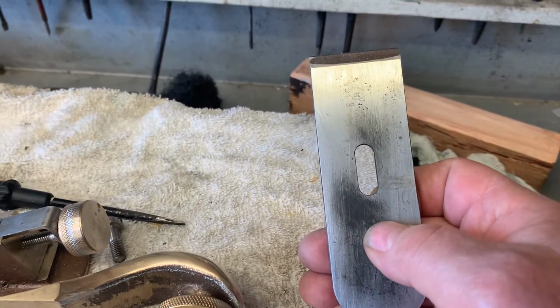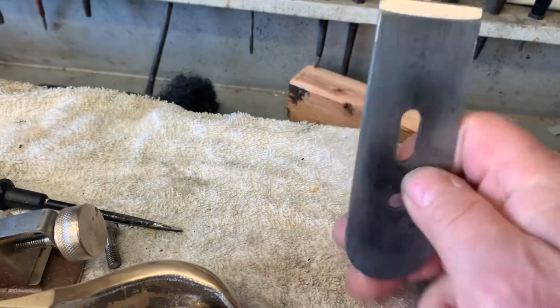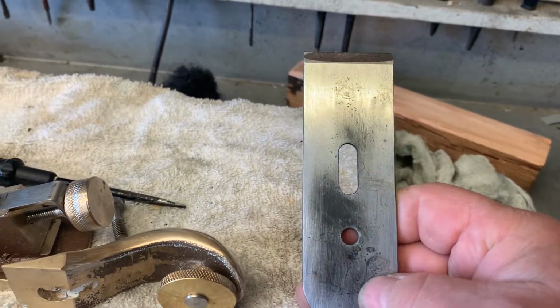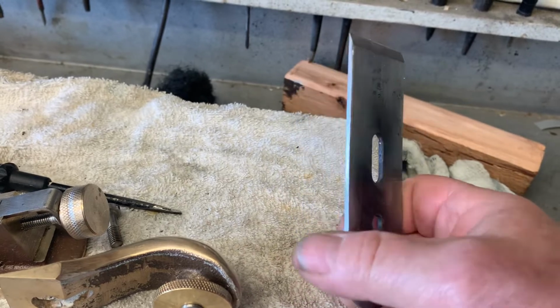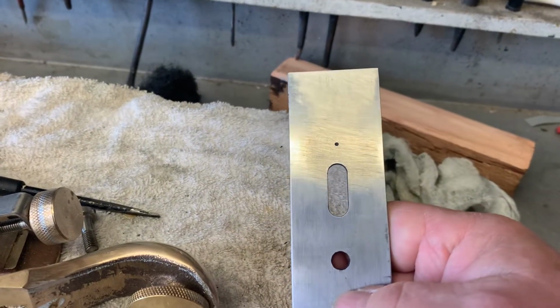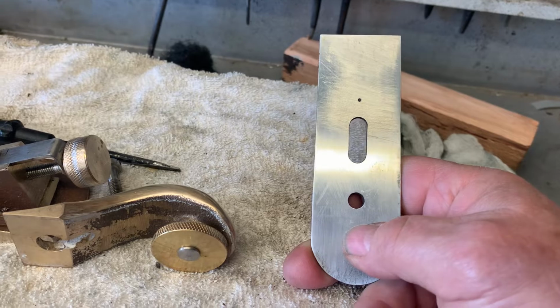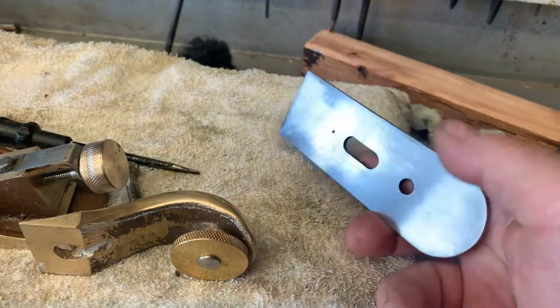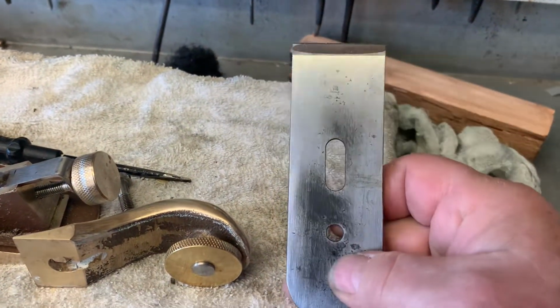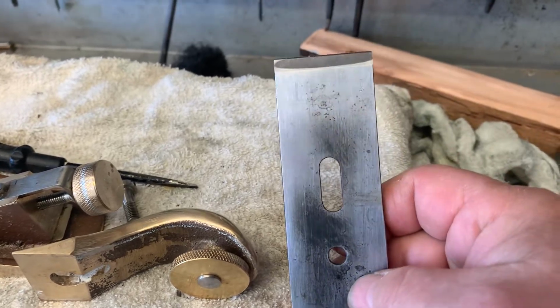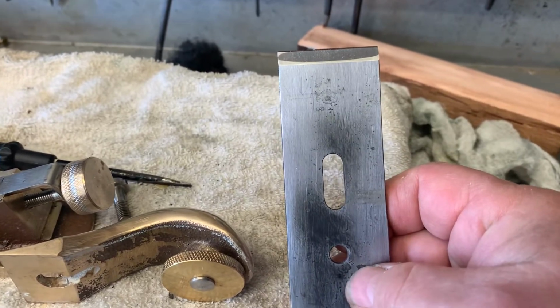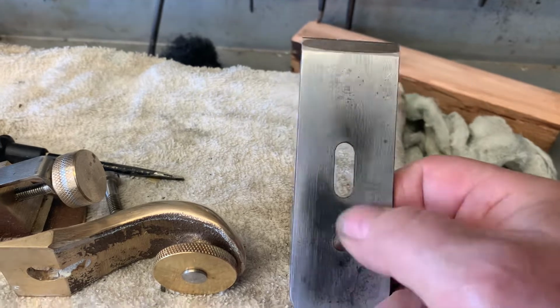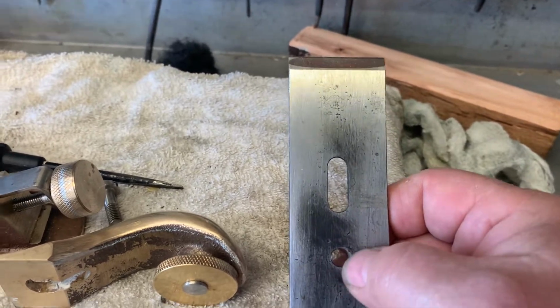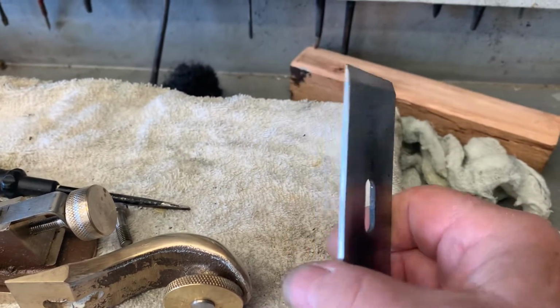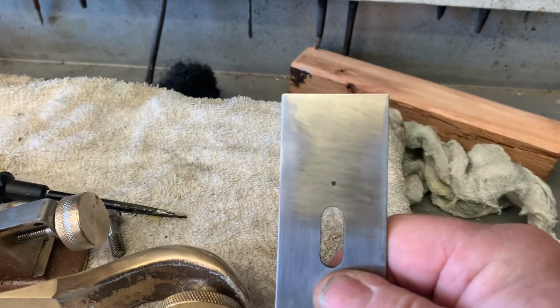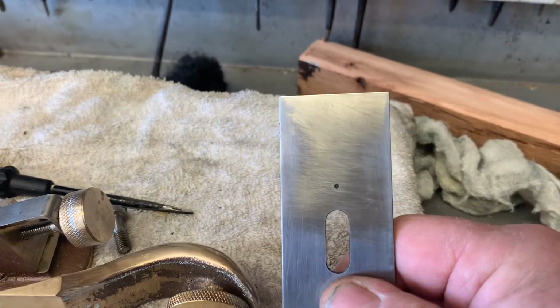And so when we're making that, we machine it all up, and at that point it's still quite soft. So what we do is we put it in the furnace, and we heat it up to critical temperature, which is about 815 degrees C, and quench it into oil. I quench this in canola oil, which is a good quenching agent for this type of steel. Different steels have different types of quenching oils. And at that point, once we quench it, it becomes very hard like glass, and it's brittle.